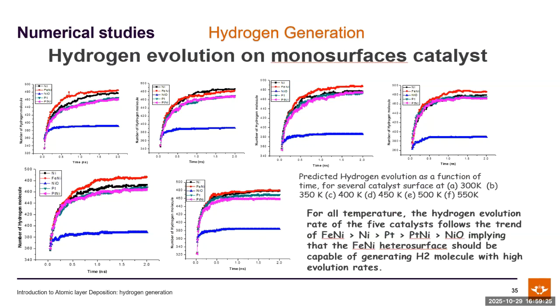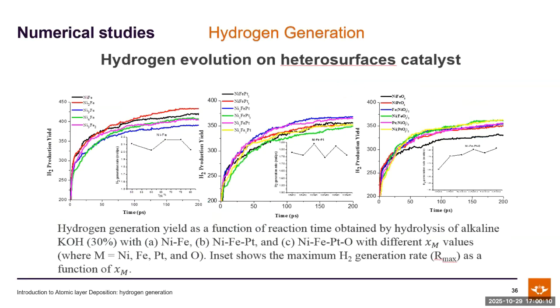Okay, so the conclusion here is, you can see all the diagrams. You can see here is nickel iron. The performance of nickel iron is better than nickel, better than platinum nickel, and better than nickel oxide. I'm not saying this is 100% correct, but it gives us the first intuition. Nickel iron actually gives us the best performance, which is wonderful, because platinum is so expensive. And nickel is also good. A lot of alkaline hydrogen generation actually did use nickel, but we found nickel iron actually gives us the best performance.